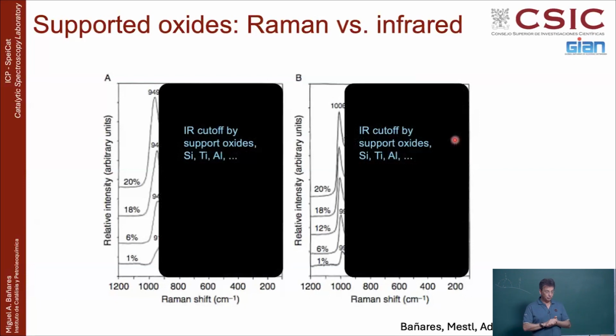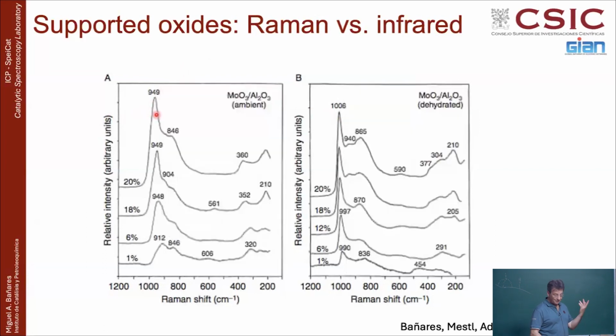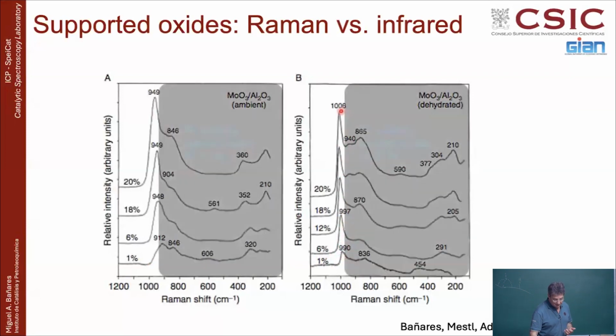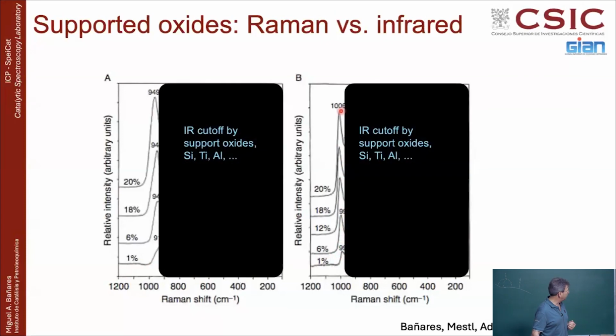This is what we see if we want to use infrared. The cutoff will allow you to see something. The humidity, yeah, okay, we see that there is a redshift, at 1000 in dehydrated, 940 hydrated. Okay, you do see something, but you cannot see as much as this. Not only that, even in the molybdenyl group, as you increase the coverage, as it goes from isolated to polymerized, you see that the frequency increases from 990, 997, all the way up to 1006. Even the position of the peak is also reporting how polymerized this material is. So that's why I like Raman, because I'm looking at supported oxides. Infrared is very good, but it has this limitation with the cutoff.